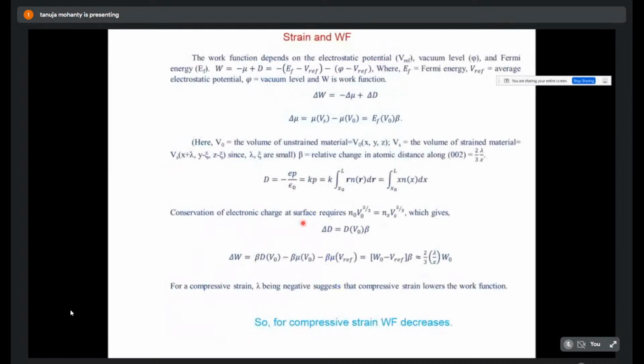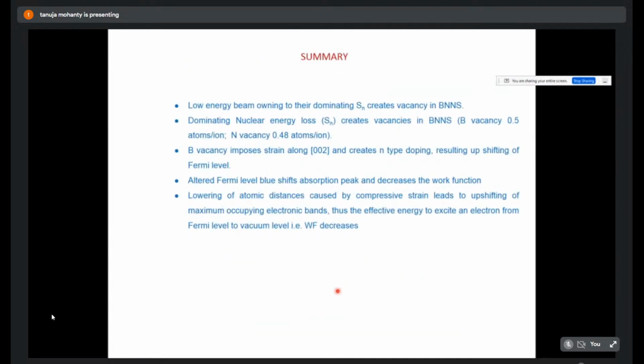And we have done a theoretical calculation of how the WF will change using the strain. Theoretically it says that the delta W should go in a negative way. So the compressive strain lambda becomes negative, and that lowers the work function. So we find that compressive strain lowers the work function of the hBN.